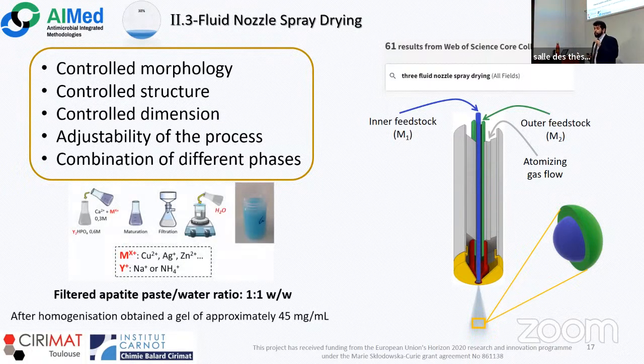And to do that, we worked toward obtaining physical gels based on our apatite synthesis. We just emulated the same synthesis that we showed before, but after the phase of filtration and washing, we rediluted the phases in order to obtain these tiny physical gels.